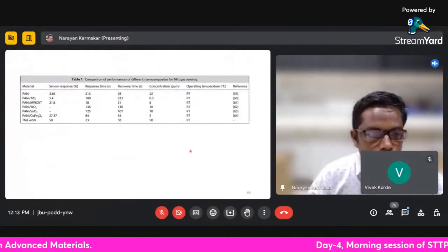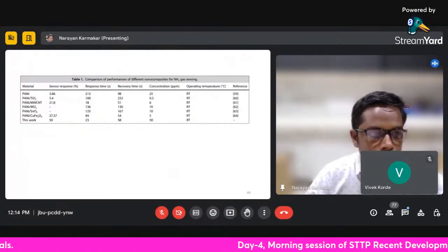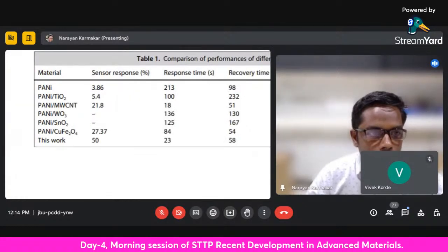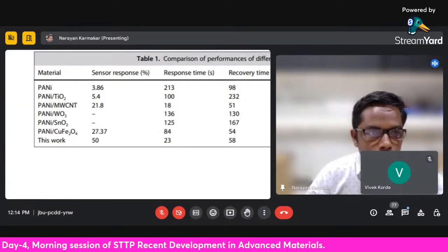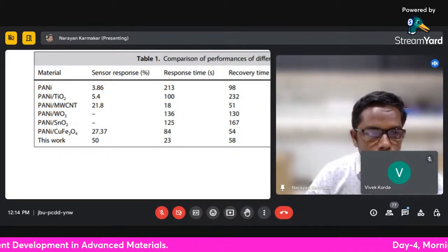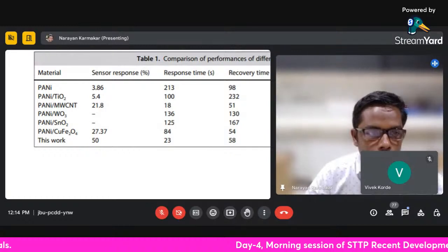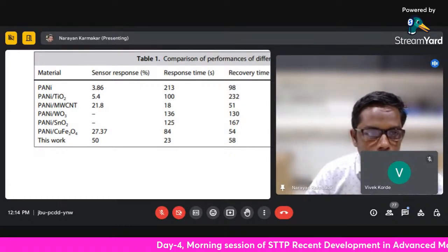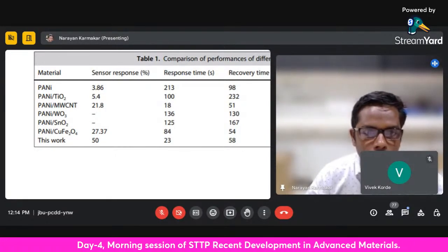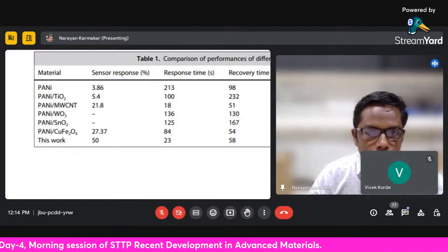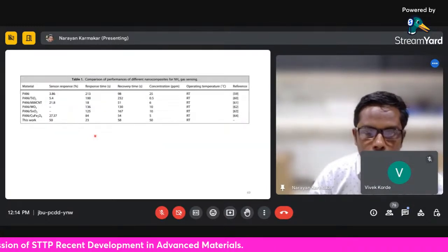So this is the comparative study of PZ10A2 as compared to the other results. In this case, the sensor response for the pure Pani is about 3.86%, and for different nanocomposites it is 5%, 21%. But in this work, we have achieved a sensor response of about 50%, and also the response time and recovery time are improved a lot.